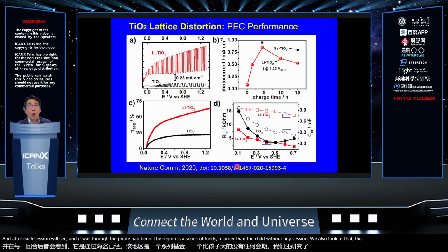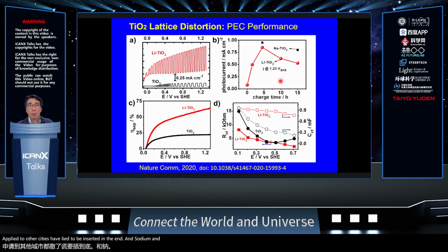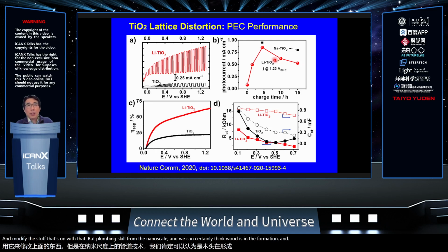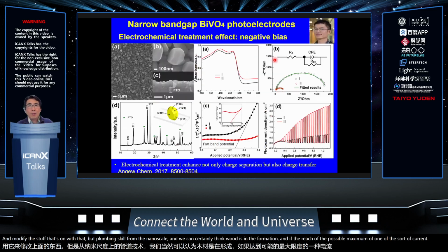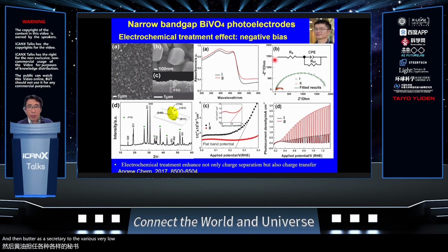We also looked at how this method can be generically applied to other systems, like inserting sodium and other species. They also show some effect, not as significant as lithium, but certainly an effect. So these two examples give us confidence that for one material, TiO2, if we can understand the structure and modify it from the atomic scale, from the nanoscale, we can certainly improve the PEC performance and reach the possible maximum of the photocurrent. But as I said, TiO2 is a very wide bandgap material, and it still cannot reach a very high solar-to-hydrogen conversion efficiency.